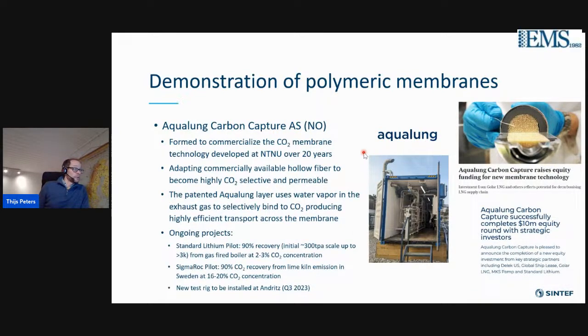Aqualung Carbon Capture is a company that was established 2 to 3 years ago to commercialize the CO2 membrane technology developed at the NTNU over the last 20 years. They are adapting commercially available hollow fibers with a patented selective layer to become highly CO2 selective and permeable. Also, this patented layer uses water vapor, so it's a facilitated transport membrane, and it uses the water vapor in the exhaust gas to selectively bind the CO2, producing a highly efficient transport across the membrane.